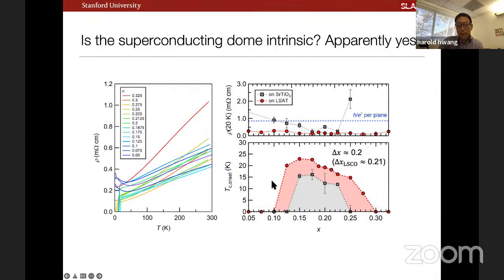So going back to this question I told you about from early days in this work, that we had this observation that there was a resistivity minimum in the normal state that corresponded to the superconducting dome. So you can ask, is this really an intrinsic dome, or is it actually a manifestation of disorder, right? And so now by moving to LSAT substrates, we can grow across the superconducting dome, and the low temperature normal state resistivity is quite low, and it's comparably low across a very broad range of doping. So we're a factor of 5 or 10 below a scale approximately of kF l equal 1.